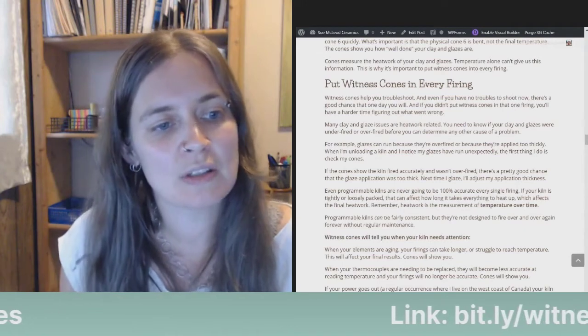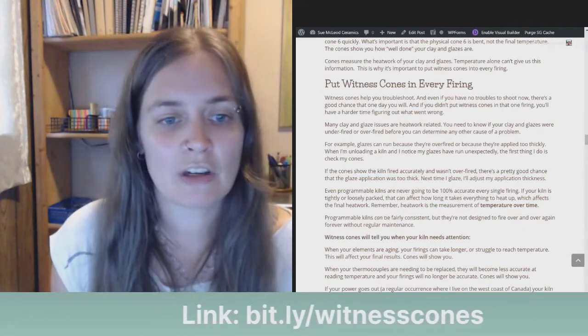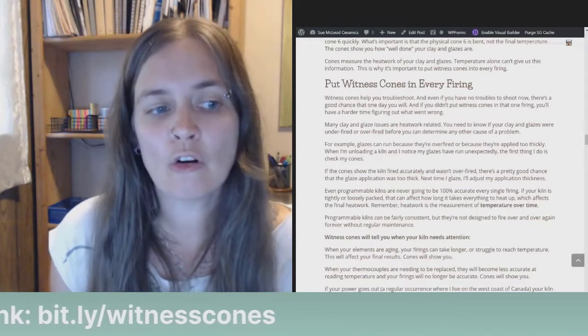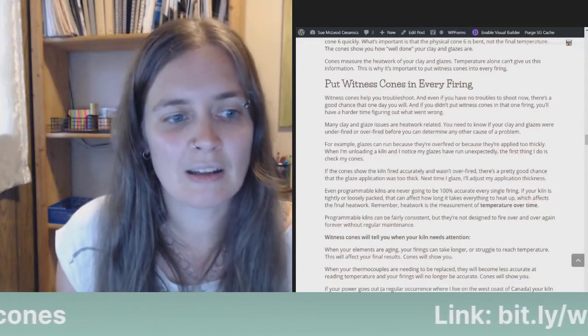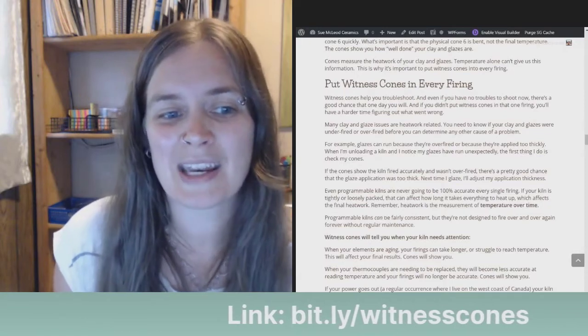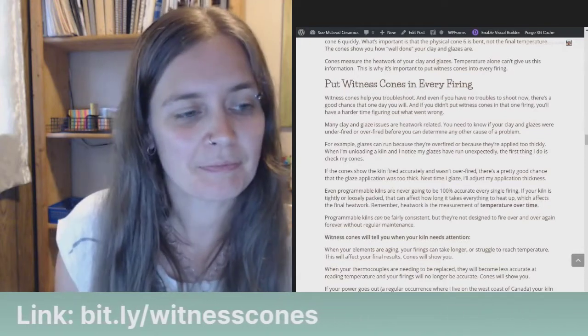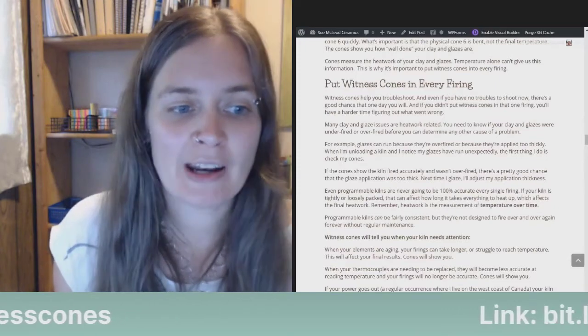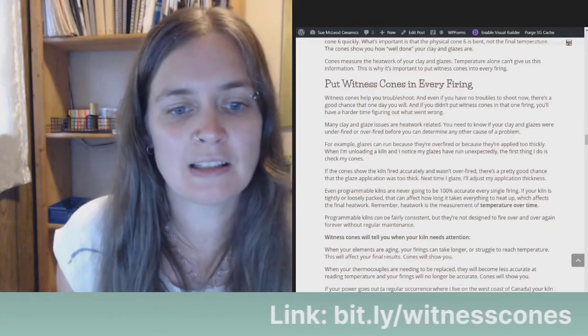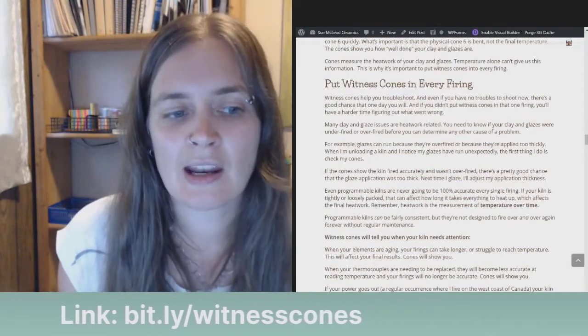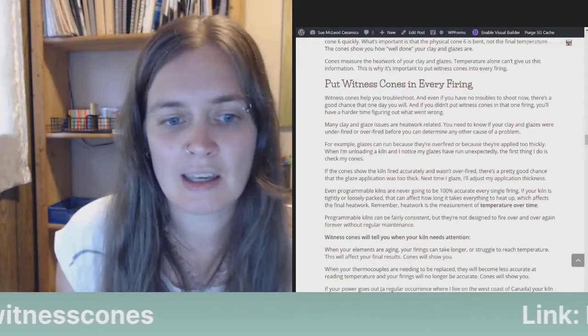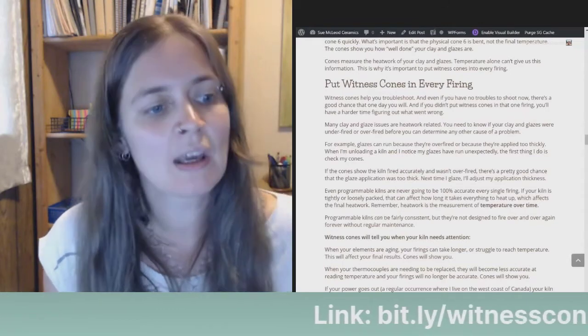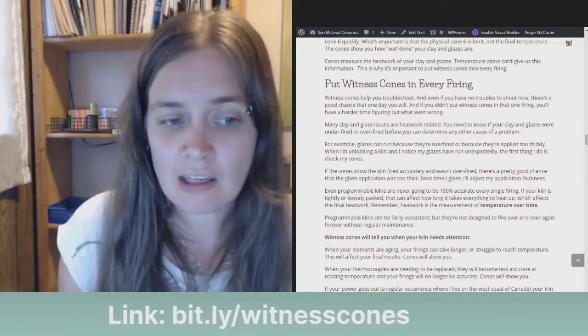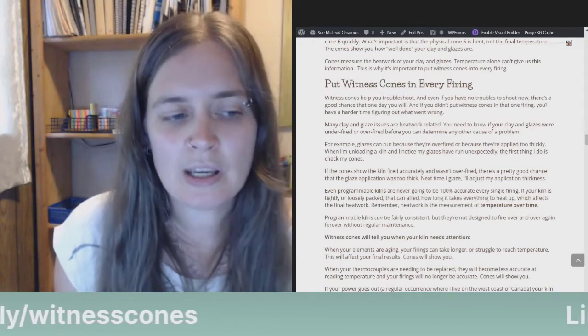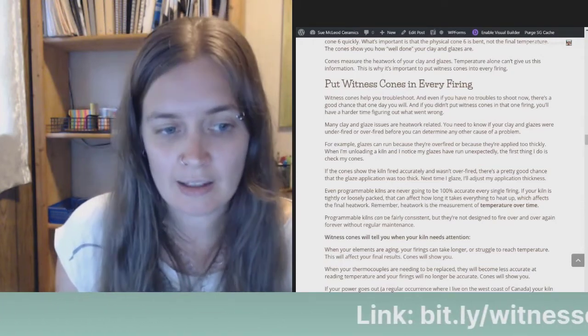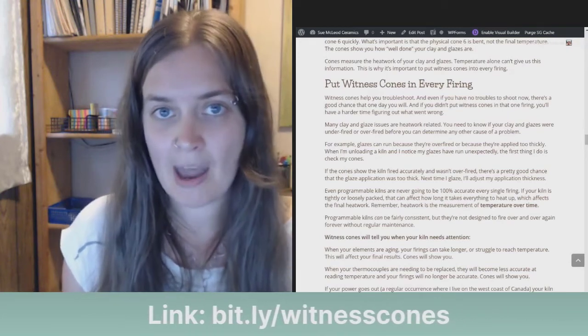Many clay and glaze issues are heat work related. You need to know if your clay and glazes were underfired or overfired before you can determine any other cause of a problem. For example, glazes can run because they're overfired or because they're applied too thickly. When I'm unloading a kiln and I notice my glazes have run unexpectedly, the first thing I do is check my cones. If the cones show the kiln has fired accurately and wasn't overfired, there's a pretty good chance that the glaze application was too thick. So next time I glaze, I will adjust my application thickness.